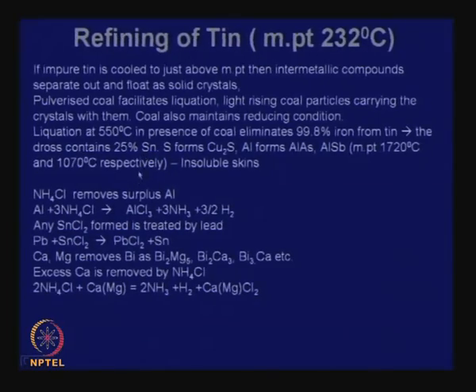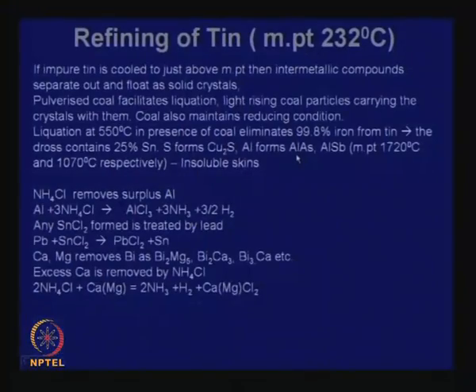Then we can remove copper by adding sulfur. We can add aluminum to remove arsenic as aluminum arsenide. Also, we can remove antimony impurities by adding aluminum. The melting point of one is 1720 degrees and of the other 1070 degrees. So, if we add aluminum powder, we will form insoluble skins that contain these solids.